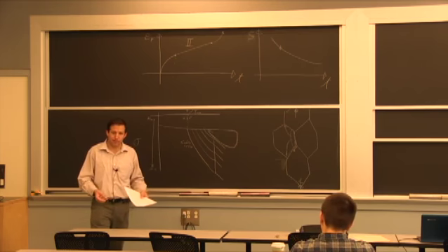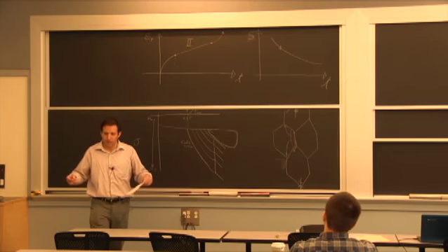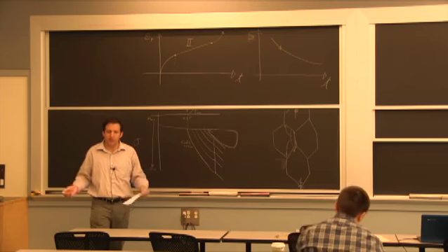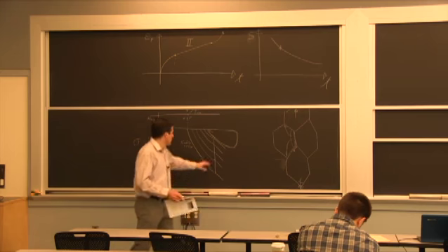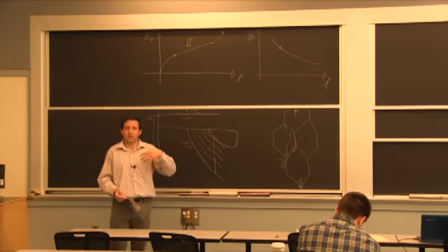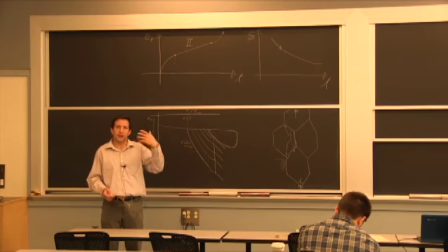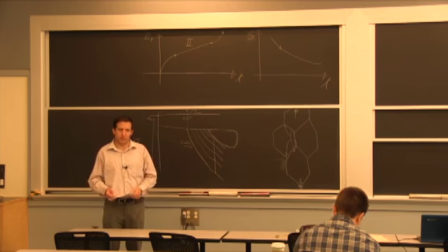So you're forming them, and then at the same time you recombine them to reduce your defect density. So in this range of temperature, you can be deforming and you can think of it as you always have about the same amount of dislocations. Some of them just come and some of them recombine and disappear.